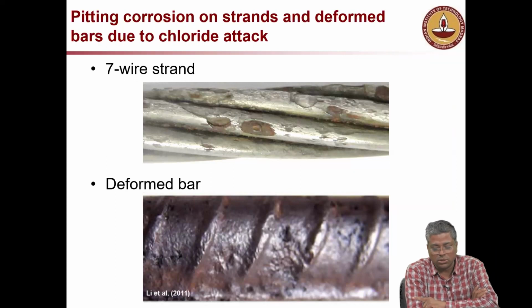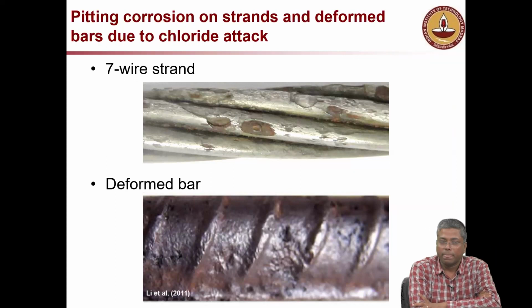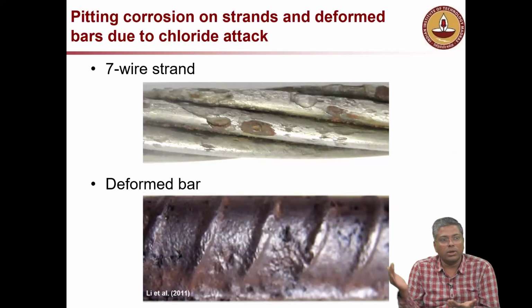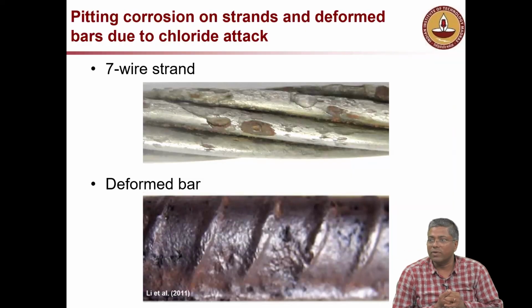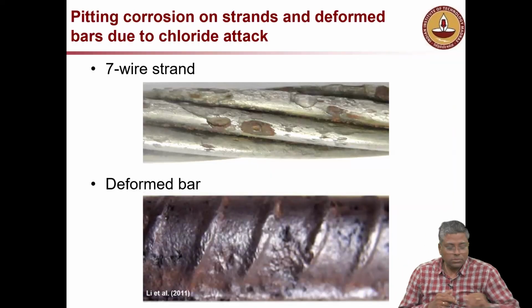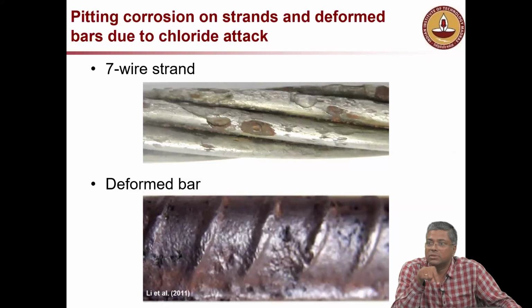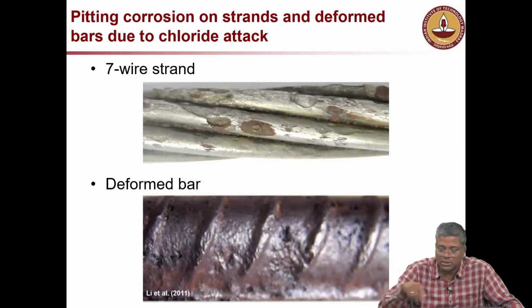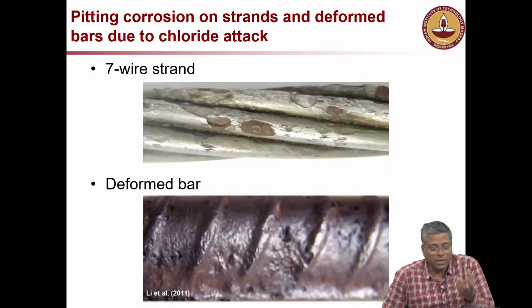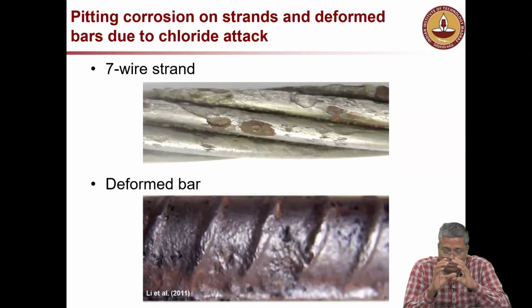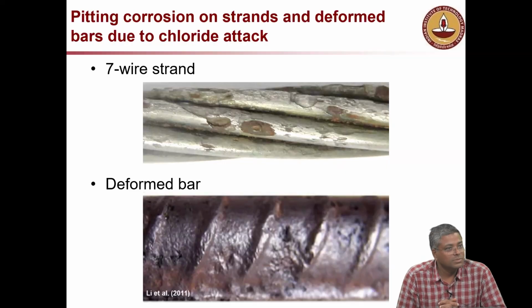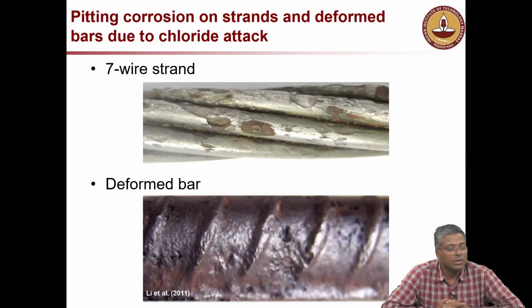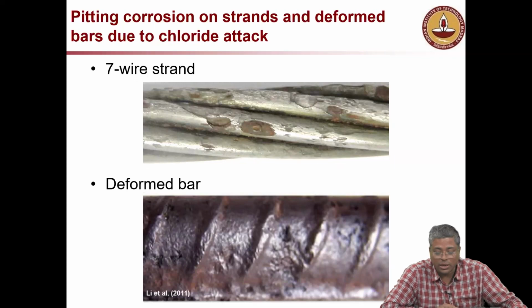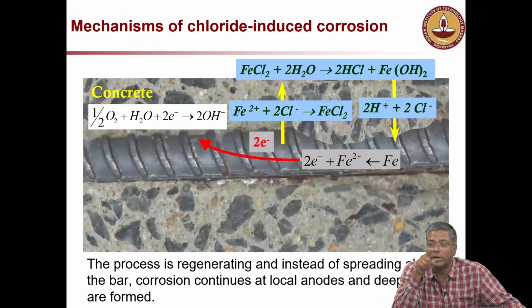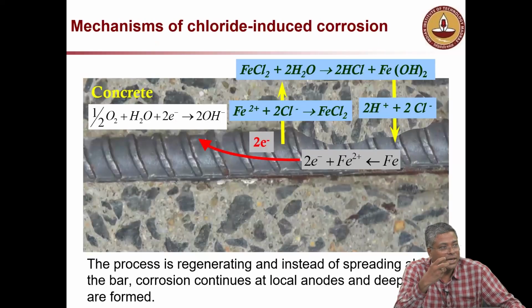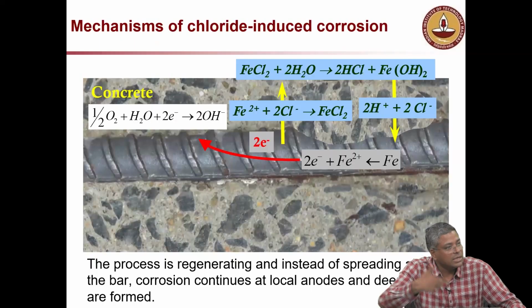If it is carbonation induced corrosion, it will not look like this. It will be smooth, layer by layer removal is what we experience in case of carbonation induced corrosion. Okay, so you can see the pits. In this picture, if you imagine that strand over there on the top, it's like a close up of a volcano, with one pit at the center. Can you see that? So it's very clear how that pit forms. That is why it is pitting, because of this HCl on the top right. It creates that acidic nature at the center of the pit, and then it keeps growing there.